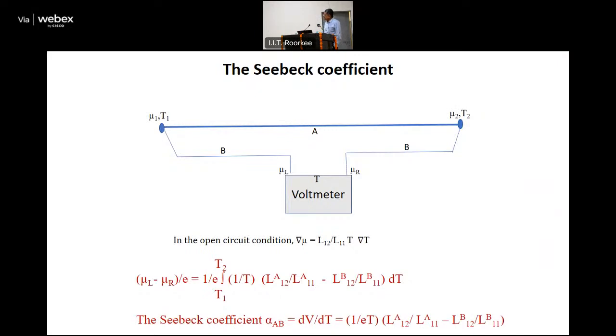Take the derivative of this potential. Remember, this mu divided by e is simply the voltage. If you take the derivative, you simply get dV by dT, which is the Seebeck coefficient. And that is simply this quantity: L12 by L11 for A, and L12 by L11 for B. So this automatically tells you that each material is characterized by its own Seebeck coefficient, if you establish a standard, which depends on this ratio of L12 by L11.